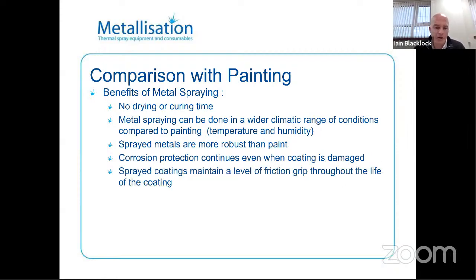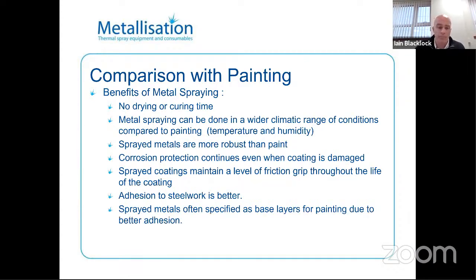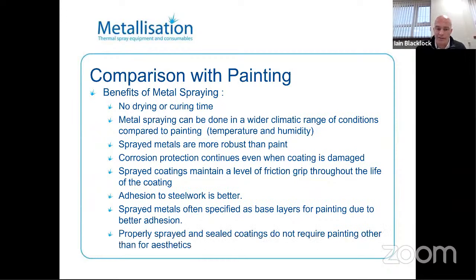Sprayed coatings maintain a level of friction grip throughout the life of the coating. What this means is that if after so many years you have to go back and freshen up the aesthetic paint coating, there will still be a friction grip underneath, which the paint can adhere to. And the adhesion to steelwork is typically better than paint spraying as well. Sprayed metals are often specified as base layers for painting due to the better adhesion. And properly sprayed and sealed coatings do not actually require painting other than for aesthetic purposes, because the corrosion protection is covered by the thermal spray zinc.